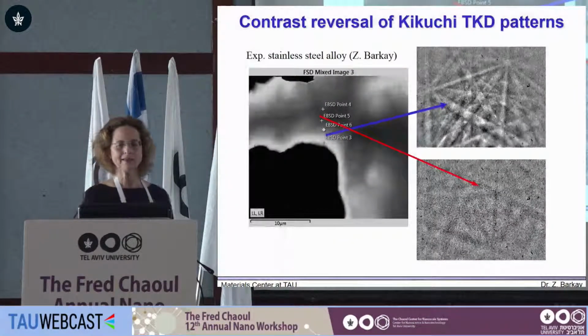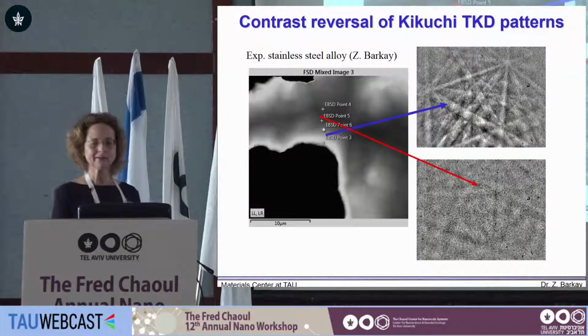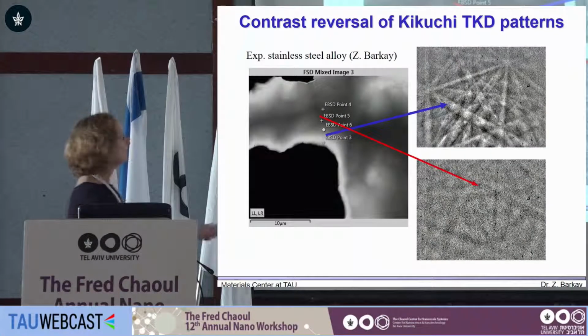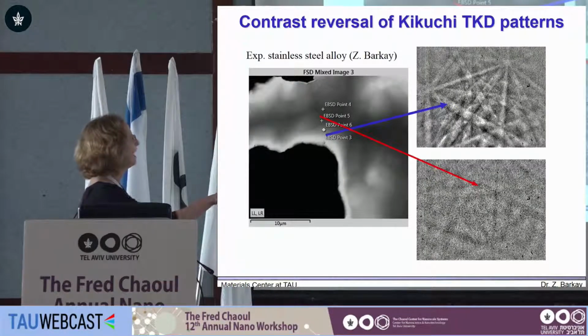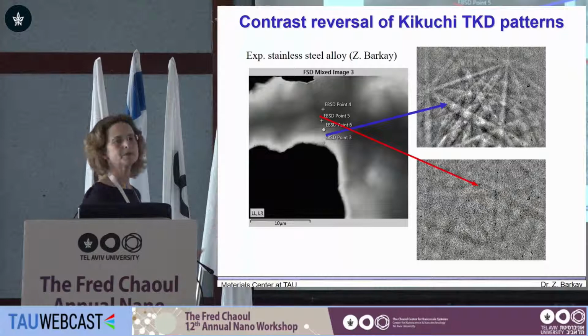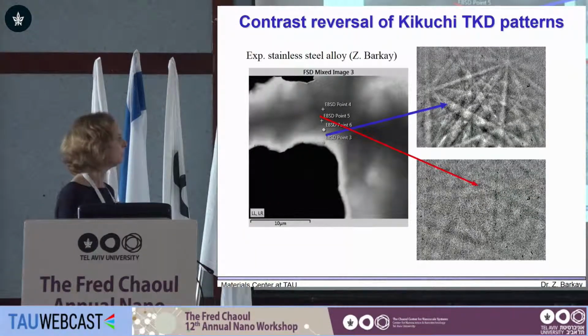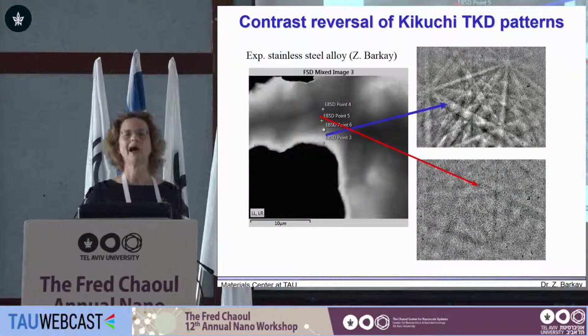A very nice and interesting result here is about contrast inversion. We are usually accustomed to this picture where we have high intensity at the center, but when we move about and around, we may have also contrast inversion. This contrast inversion is actually an effect on the outgoing beam.